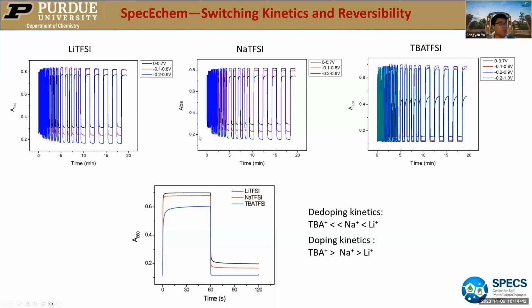Here are a few examples of the absorption switching for three electrolytes. And I also compare their kinetics. For the de-doping process, TBA has the slowest kinetics and lithium has the fastest. But in the doping process, it's reversed. So TBA has a faster doping process and lithium has the slowest doping kinetics.